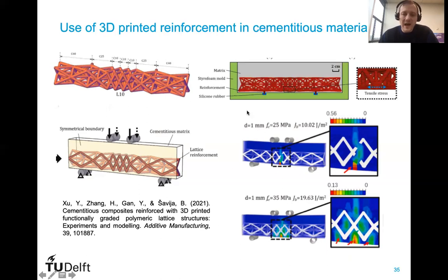So we can say, okay, what happens if we change the reinforcement, if we print a stiffer one or a stronger one? And what we show is that if you adjust the properties of the reinforcement, the stiffness and the strength, you can also get multiple cracking inside of these materials. So we showed that in terms of models. We were not able to achieve that in terms of experiments, but what we know now is which direction we need to develop our design in order to get certain properties. So in this way, the models inform the experiments.